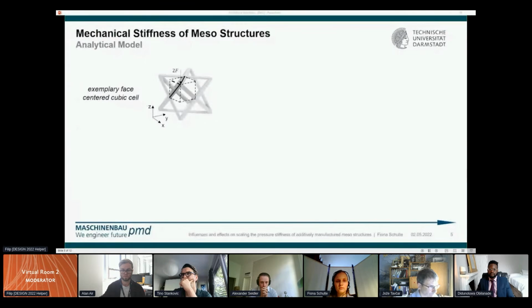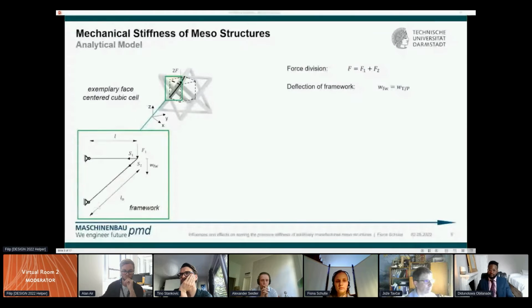The analytical model of a face-centered cubic cell is shown here. To reduce the 3-dimensional geometry to 2 dimensions, the struts of the upper and lower surface respectively are projected to one plane. Now 1/8 of the cell is considered, while forces and stiffnesses are portioned or added respectively to achieve the overall stiffness of the cell. The force path through the FCC cell can be split into 2 parallel paths. The first path is modeled as a framework consisting of bars and showing a deflection depending on the tensile compression stiffness of the framework.